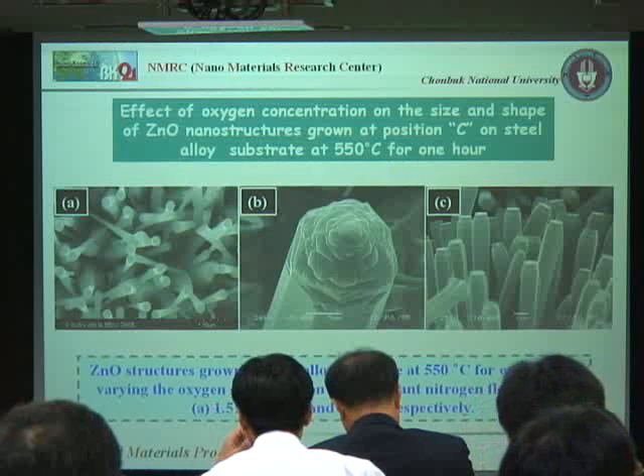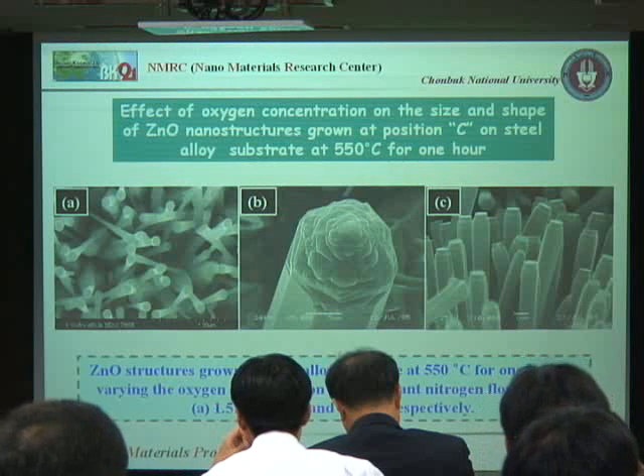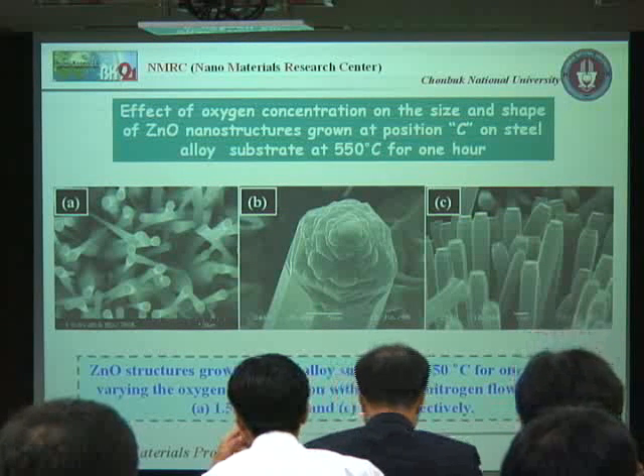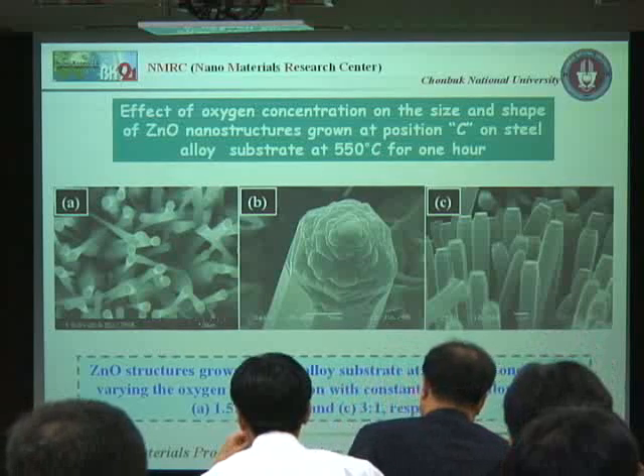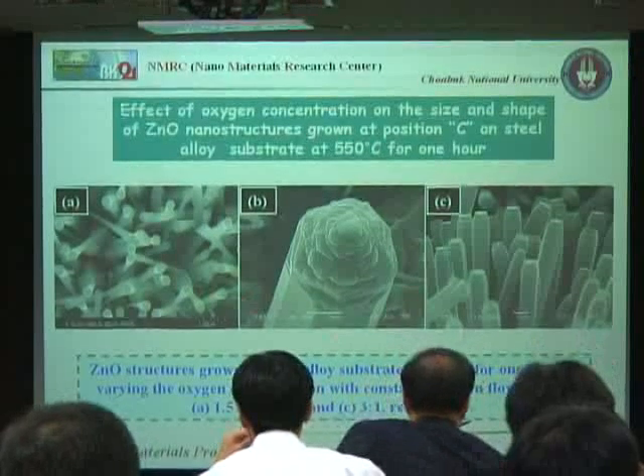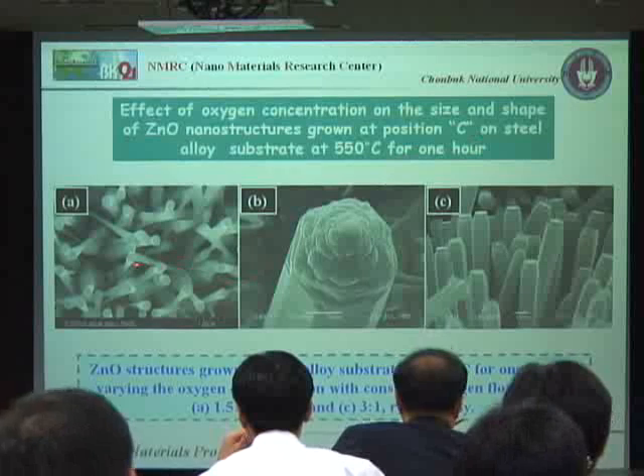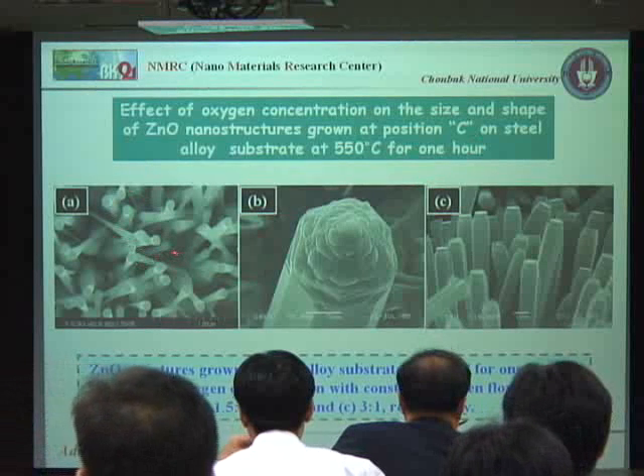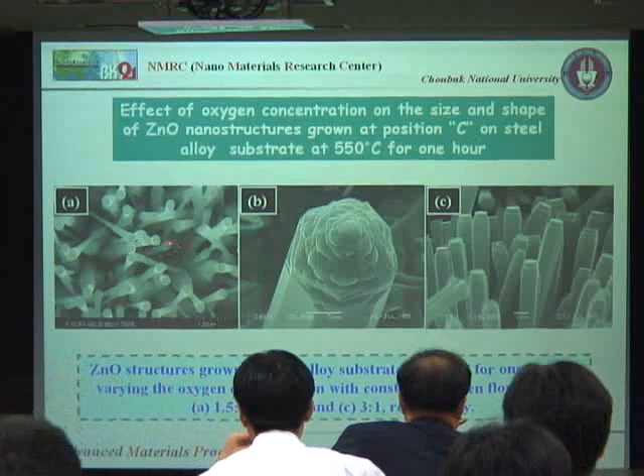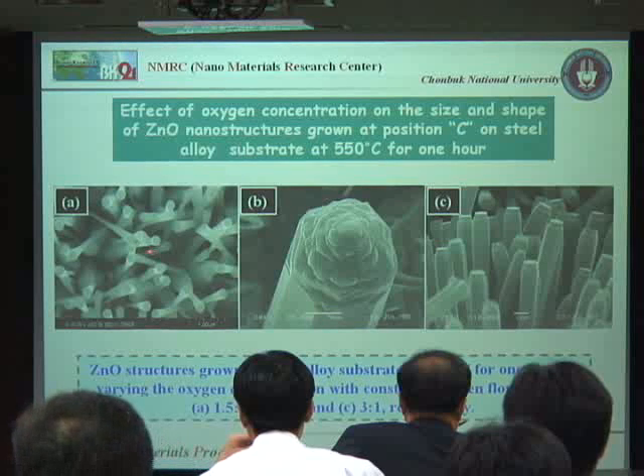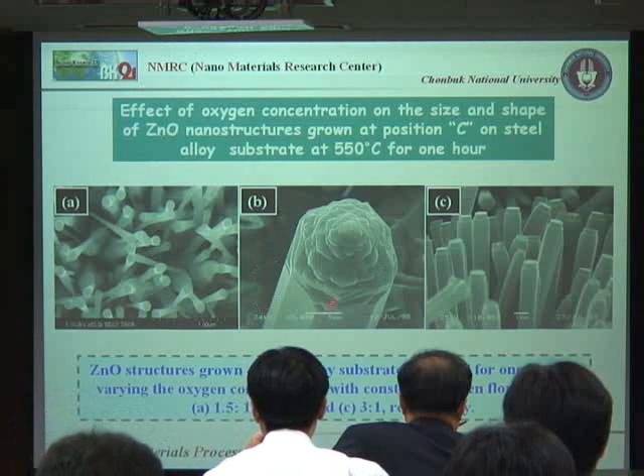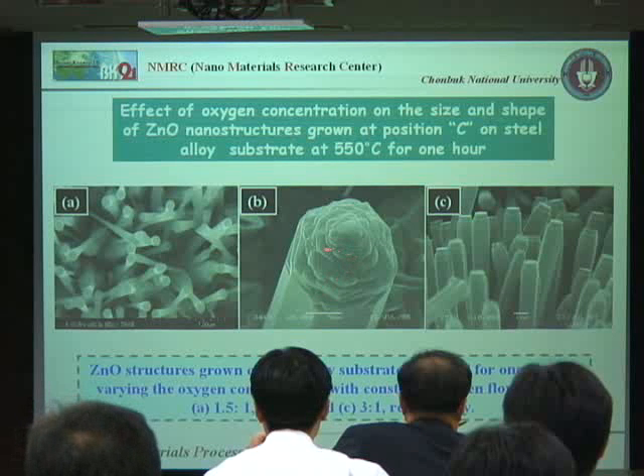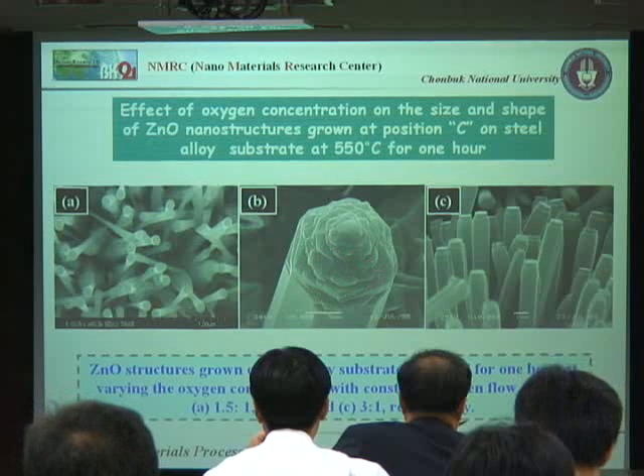So we did some more experiments, and we chose 1.5:1 oxygen and nitrogen ratio, 2:1 oxygen and nitrogen ratio, and 3:1 oxygen and nitrogen ratio. And we observed at position C, previously I described that we got these inverted nanocone structures in a high density. But when we increase the oxygen concentration, we got these microrods on the substrate.